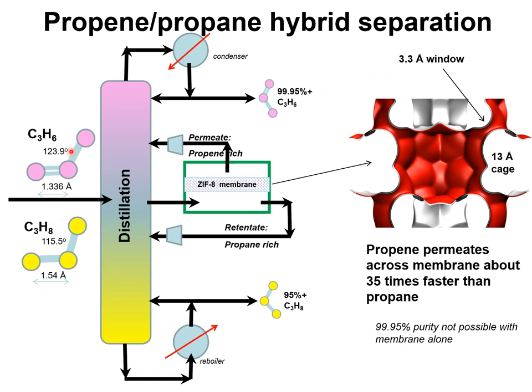The separation of mixtures of propene and propane to obtain propene of purities in excess of 99.95% is required for feedstocks to polymerization reactors. This separation is normally carried out in cryogenic distillation units that are energy intensive. A hybrid construction consisting of a combination of distillation with a membrane construct may be used to reduce the load on the condenser and reboiler, and a ZIF-8 membrane is a candidate for use in such hybrid distillation-membrane constructs.